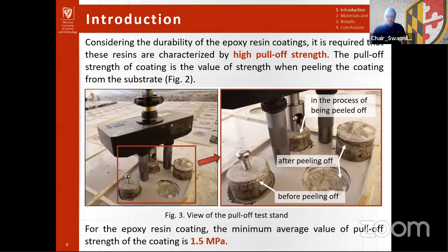Considering the durability of the epoxy resin coatings, it is required that these resins are characterized by a high pull-off strength. As you can see in the picture, the pull-off strength of coating is the value of strength when peeling the coating from the substrate. For the epoxy resin coating, the minimum average value of pull-off strength is 1.5 megapascals.